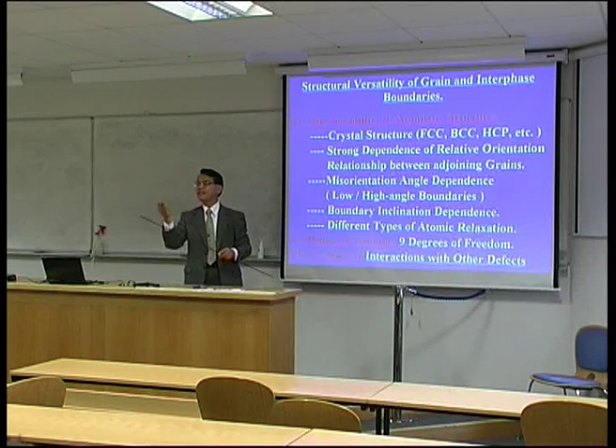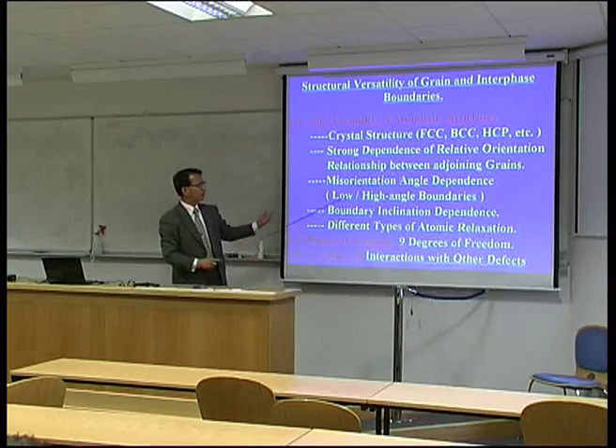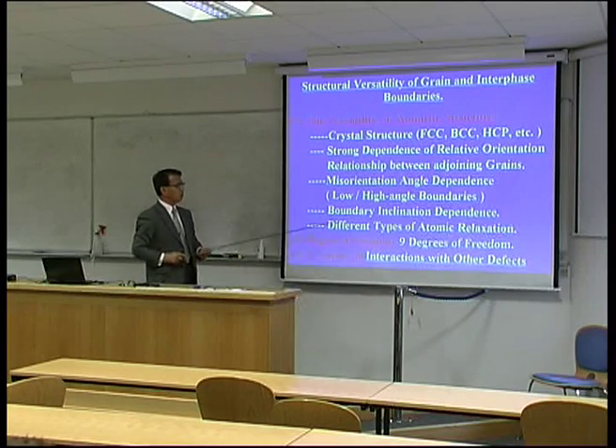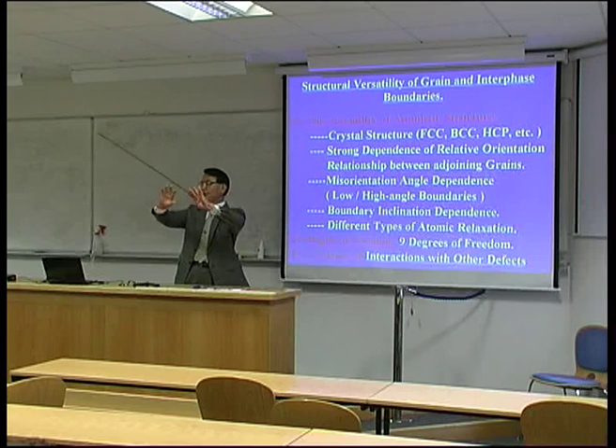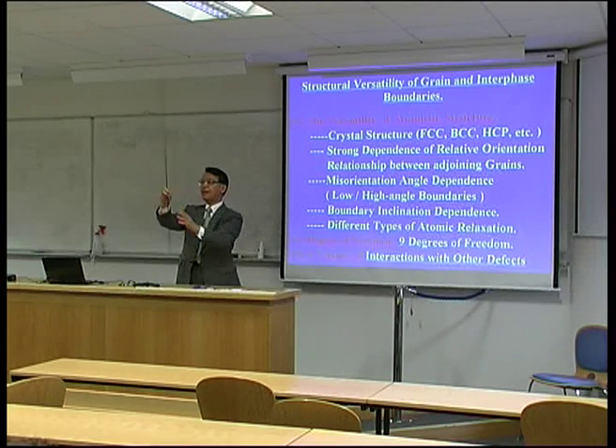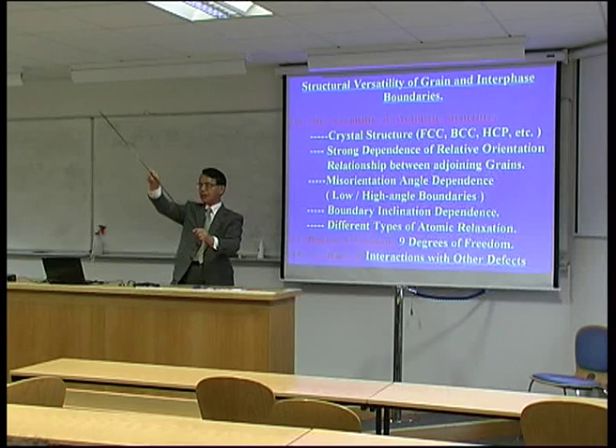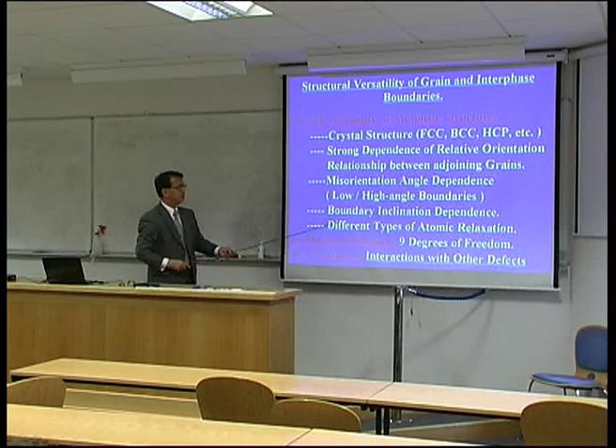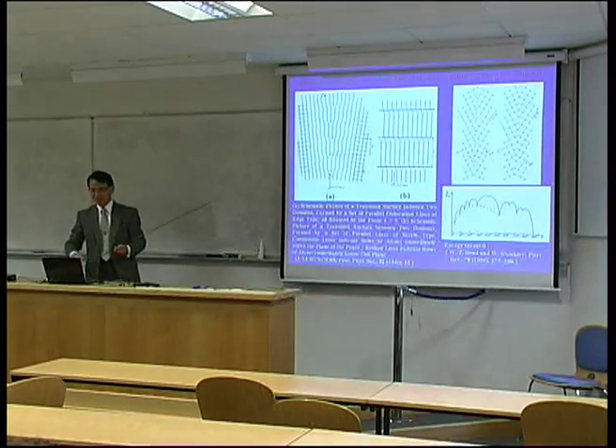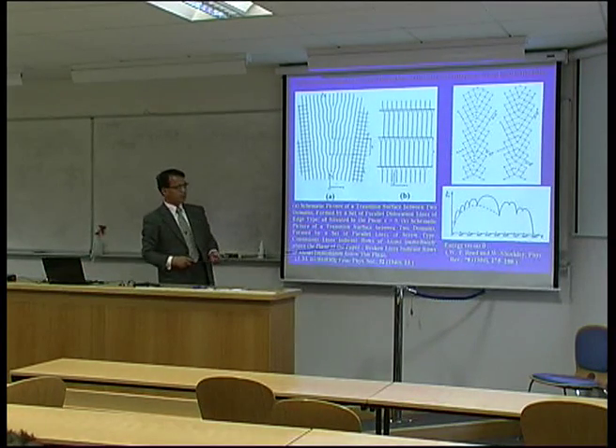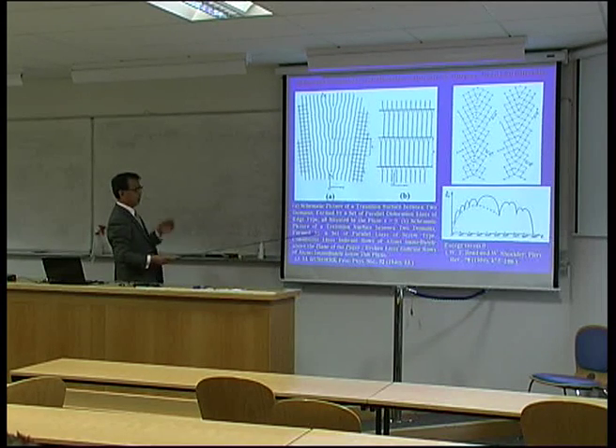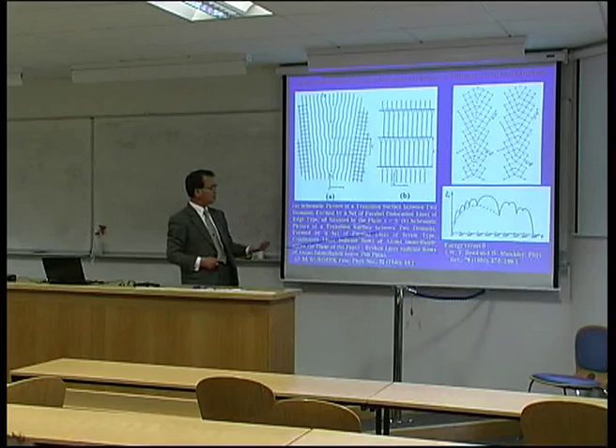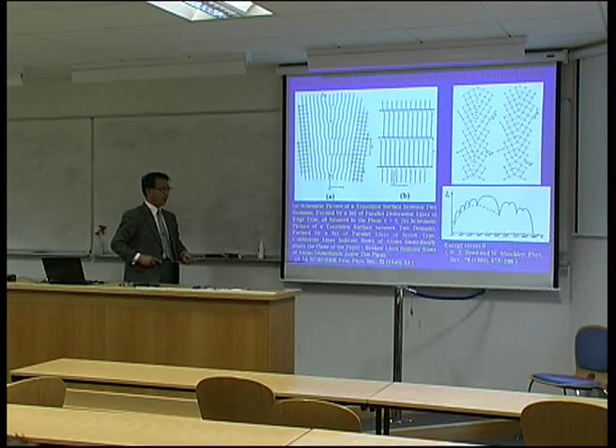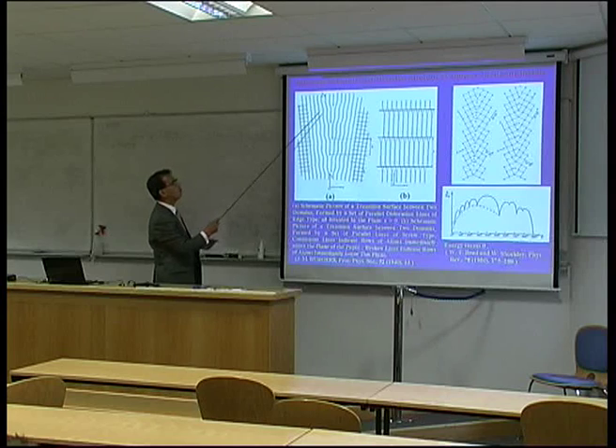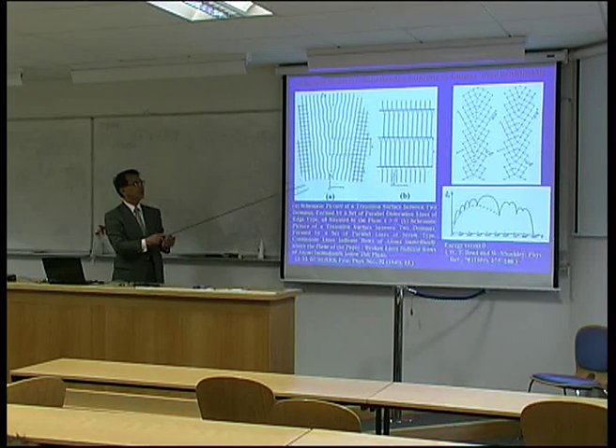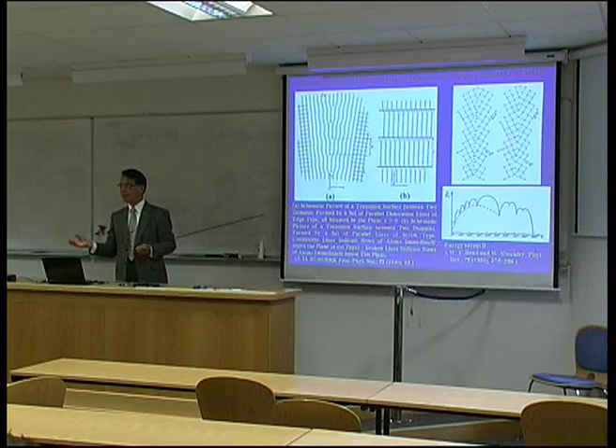Often we call it, for example, the coincidence site lattice model. Such a boundary can occur. And also, even for a constant disorientation relationship, depending on the boundary inclination, the atomic structure can be different, like this. So it's not easy to define, but soon after the dislocation theory was introduced to physics, several pioneers worked out models of grain boundary structure based on dislocations, like this.